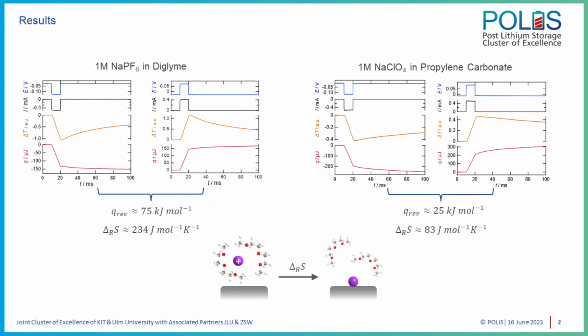In both systems, we could measure a cooling of the electrode during the sodium deposition and a warming during the dissolution of the sodium ions. And along with the behavior of the potential and the current transients, these results show that in both systems, the sodium deposition and dissolution is highly reversible. And the corresponding values for the reversible heat are 75 kJ per mole for the sodium deposition in diglyme and 25 kJ per mole for the deposition in propylene carbonate.